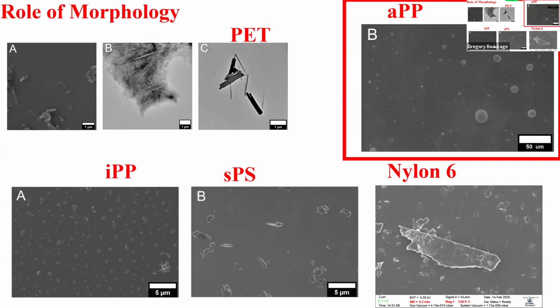You see those droplets all around? Those are 50 micron droplets. And what we think is happening is that it's making small liquid oligomers that are between those entanglement points, and those liquid-like oligomeric fragments agglomerate to give you liquid-like droplets. So that is one kind of problem, but it makes those small fragments. Everybody happy so far? But look at the analog there.